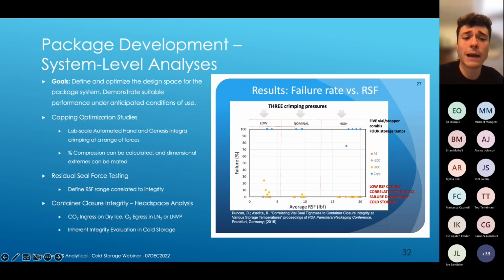And so oftentimes we'll do this lab scale using automated hand or an industrial style capper, such as the Genesis Integra, allowing us to crimp at a range of forces. Ideally, we will have samples prepared that also reflect the dimensional extremes at each of these crimp forces. So we get the full range of dimensional variation within each sealing set, but we're looking at how those different package systems perform from an integrity perspective after they've been crimped according to different parameters. And so doing this, we can actually calculate in the laboratory percent compression of that elastomer based on the dimensional tolerances, stack ups rather, that we measure before and after sealing.